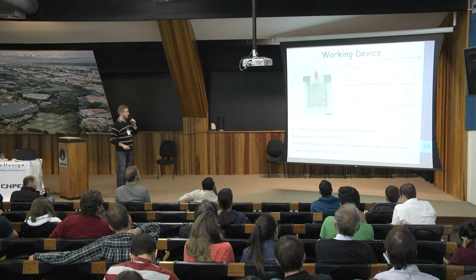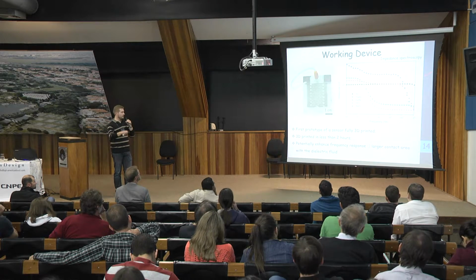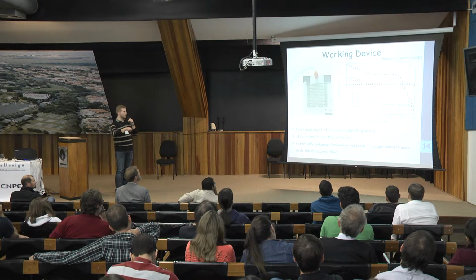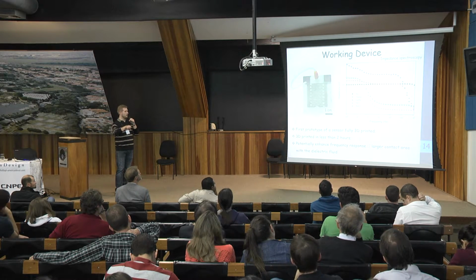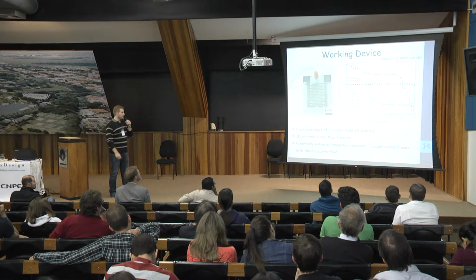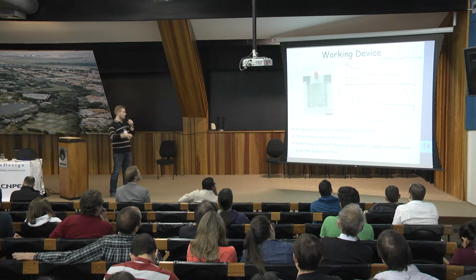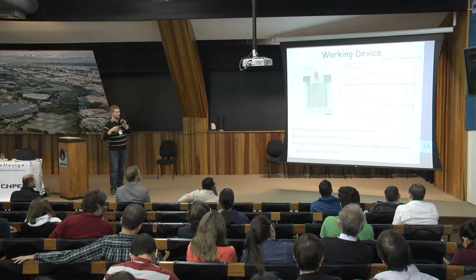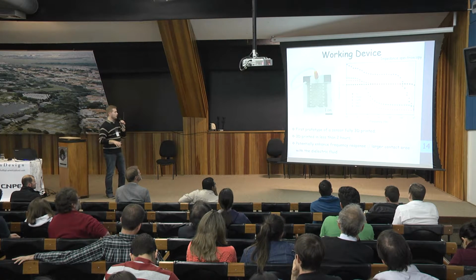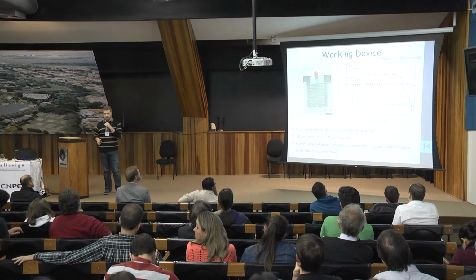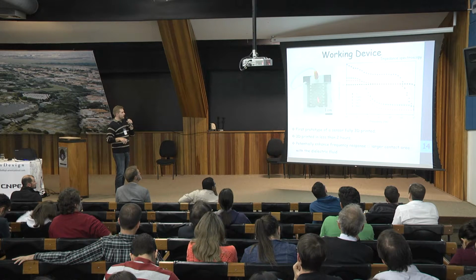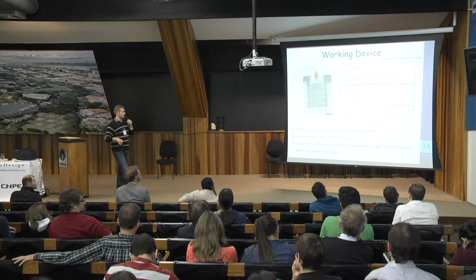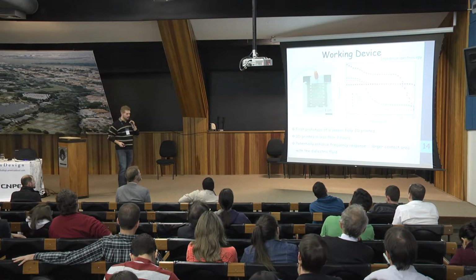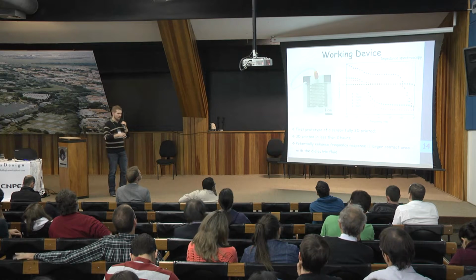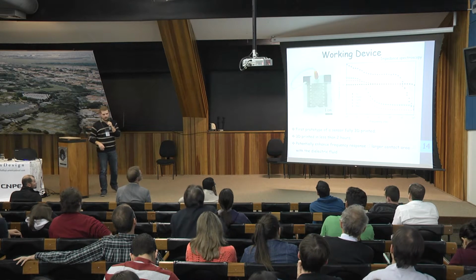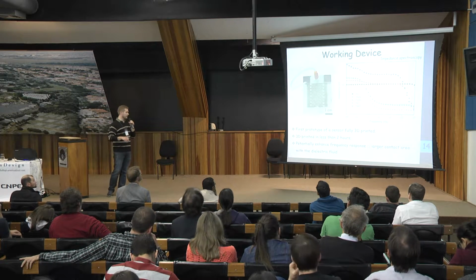With this idea, we got a working device, and when we performed impedance spectroscopy on the basic tastes, we could get a really good distinction among them. And again, this is only a 1 cm unit. If you want to go for an electronic tongue or other sensing devices, we have to deposit some nanofilm materials. However, it's interesting to point out that this device took less than 10 hours to be ready. Meanwhile, when you take into account the electrode production and the microchannel production, we would easily take at least 1 week to have this working device.